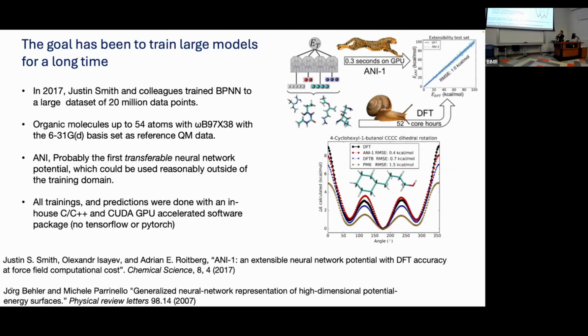So I think this is really admirable work overall, but it is also a beautiful demonstration of how transferable neural networks can be. In the case I showed you, there's one composition, cesium lead iodide, with one accurate potential. Here, there's an accurate potential for a very large chemical space of organics. And there are some tricks that, if you talk to Justin about this, he mentioned he did. We did what's called curriculum learning. So you start from some small molecules and you iterate the training to get higher and higher. But nonetheless, it worked quite well.